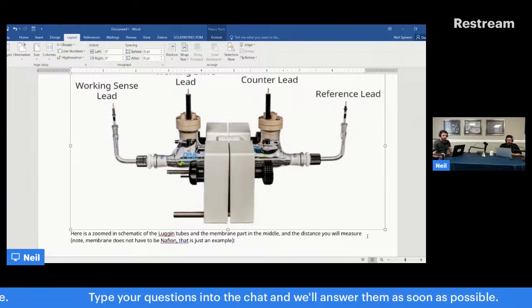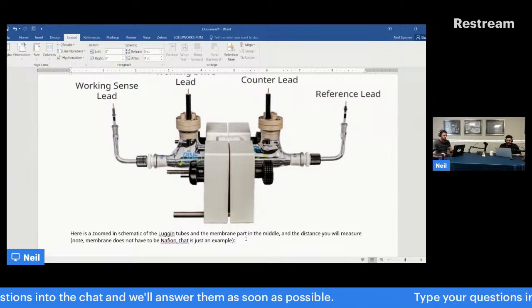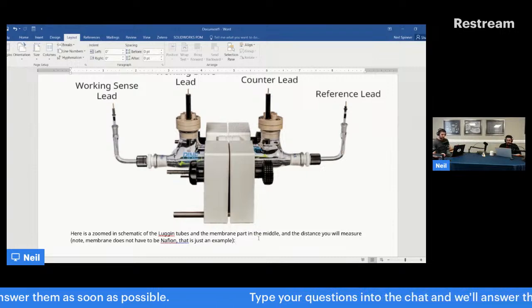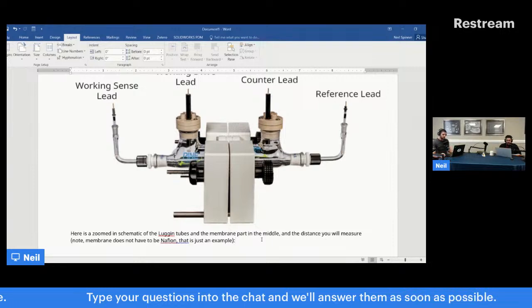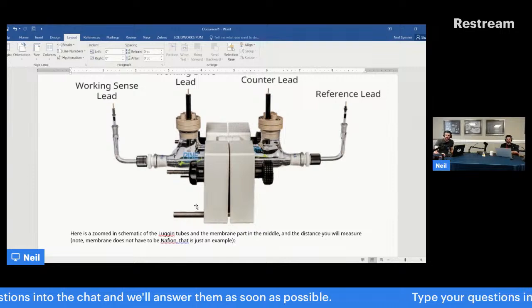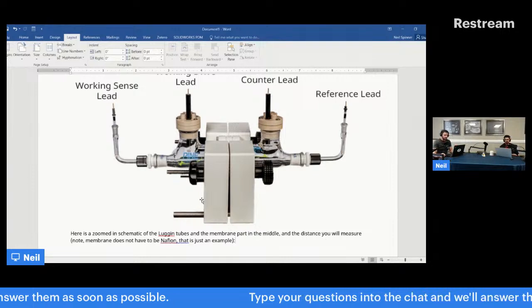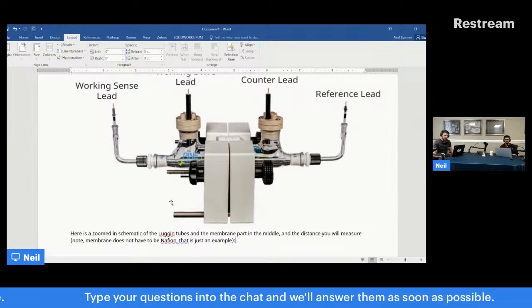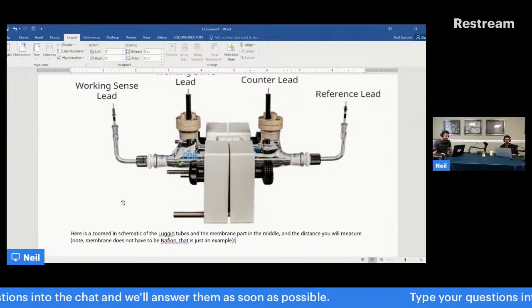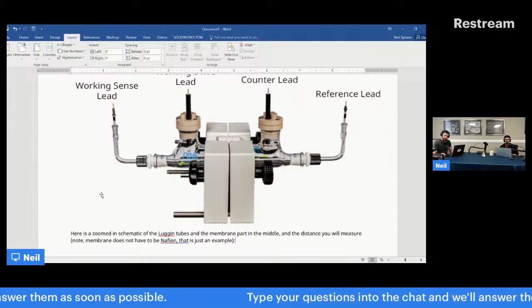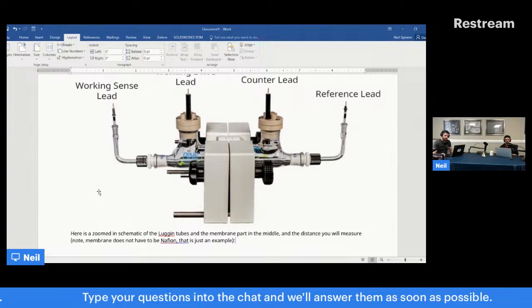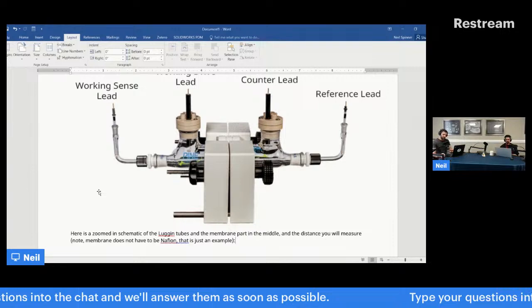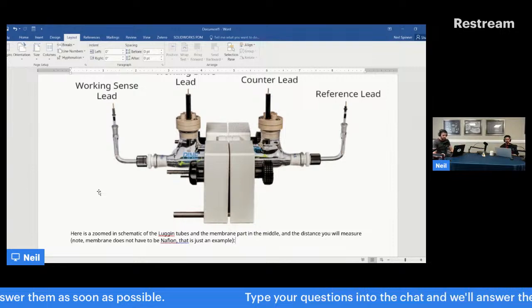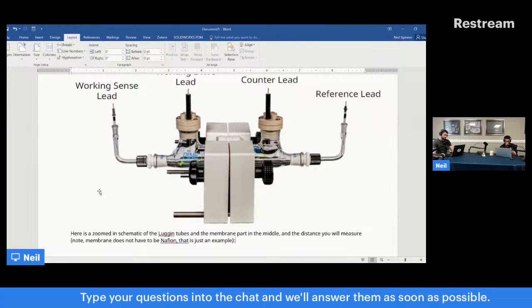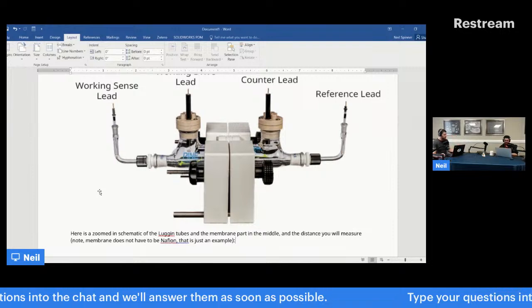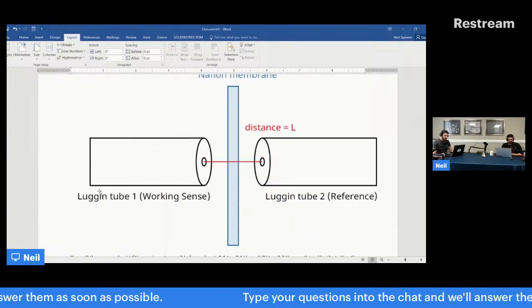So the first thing about the EIS and the RCT thing is that, as Alex said, it kind of depends. You generally are trying to measure the conductivity of your membrane. You don't want to have a faradaic reaction there. There's definitely a lot of discrepancy in EIS. I don't know if you would want to use a Randles element for your fit, to be honest, because that implies a charge transfer resistance, which implies a faradaic reaction, and you probably don't want a faradaic reaction going on. You just use plain salt solution, or if it's a Nafion membrane, plain 0.1 molar sulfuric acid with nothing else. You don't want to do oxygen reduction, oxygen evolution, or hydrogen. You want a neutral potential where nothing in particular of interest is happening.